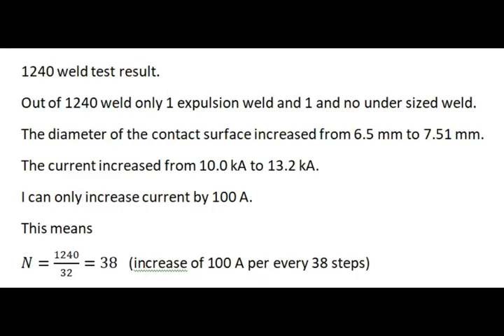Out of 1,240 welds, only one expulsion weld and no under sized weld. The diameter of the contact surface increased from 6.5 mm to 7.51 mm, and the current increased from 10.0 kA to 13.2 kA. If we increase the current every 38 welds, we can weld 1,000 non-expulsion welds in a row. We only need to tip dress the current 2,500 welds.